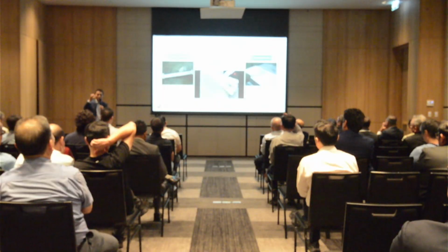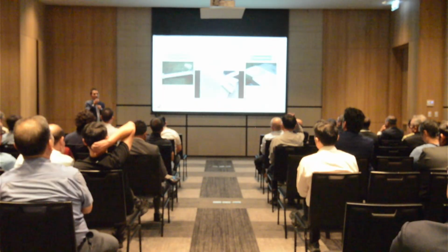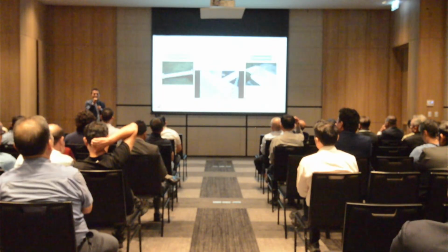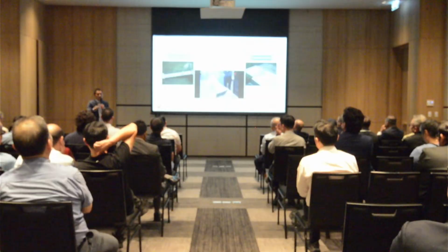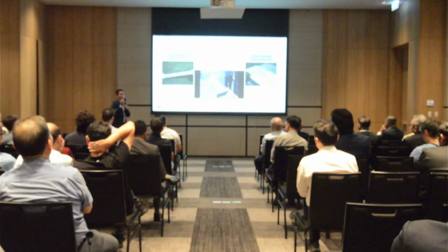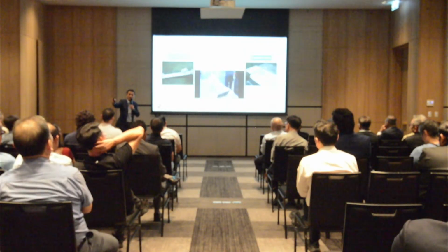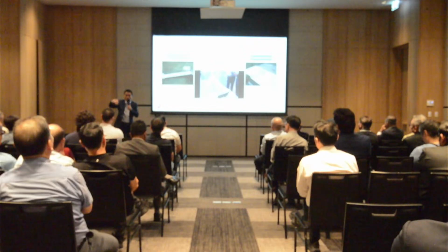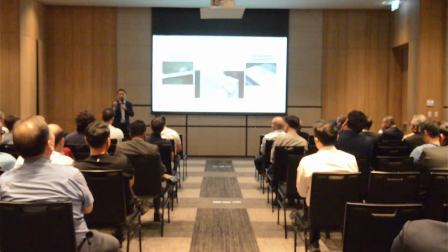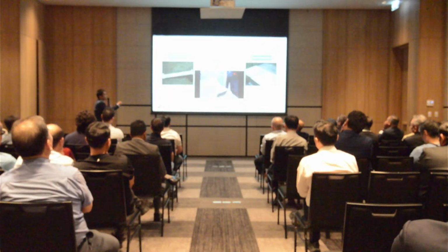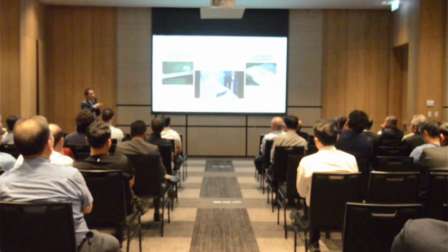When you continue to wait a long time, the solid will be remelting again because of equilibrium. But when you put this hot water with ice into a refrigerator and it cools down, reducing the liquidus, you will keep those solid particles. It will move into equilibrium conditions. That's the reason GISS is a superheated slurry. We are higher than liquidus.